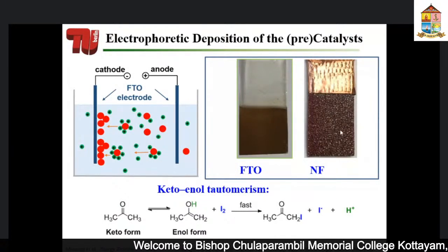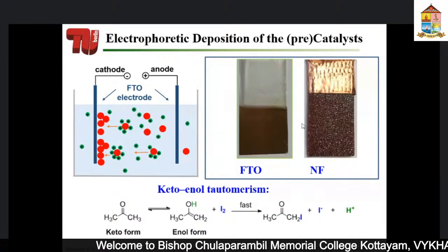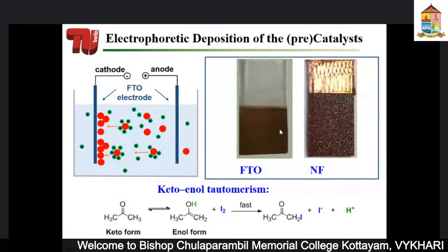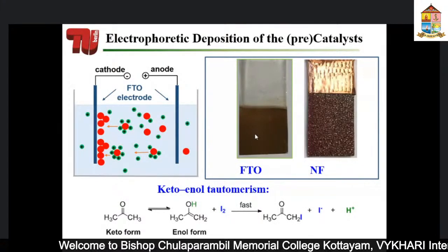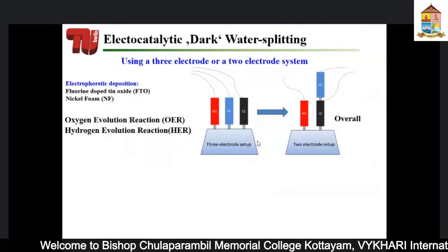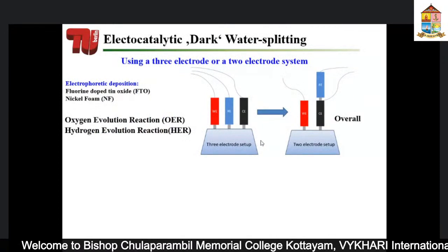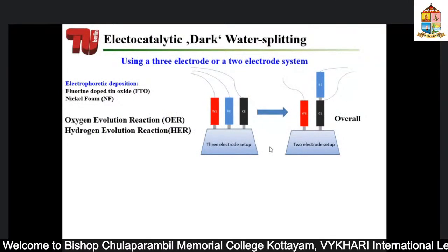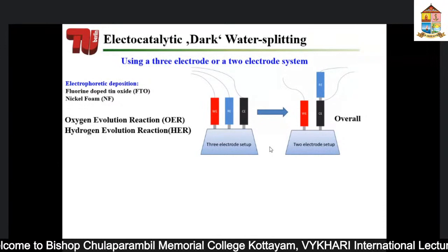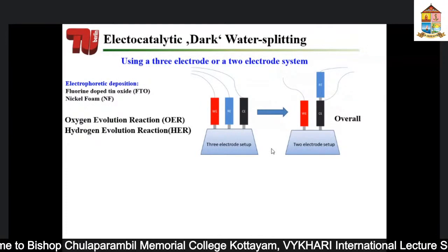And this is the same film on nickel foam. And this is a 3D porous material. So you could see that you still see the pores. And this is the flat surface. Okay, so now we made the films. Now we have to check whether it's active or not active, or whether it can produce any hydrogen or it is inactive for oxygen evolution.